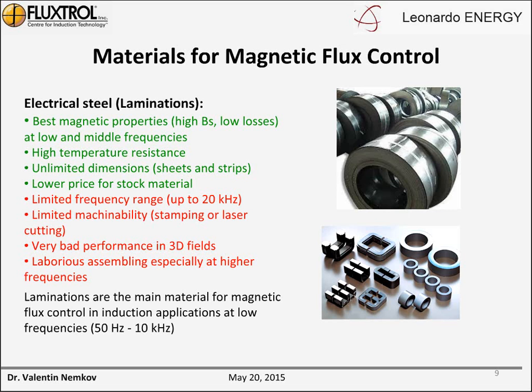The second drawback is very essential. It's limited machinability. It's stamping or laser cutting. Then, very bad performance in 3D fields. And laborious assembling, especially at high frequencies when the thickness of laminations is small. As a result, laminations are a great material for magnetic flux control in induction applications at low frequency, let's say from 50 hertz to 10 kilohertz.